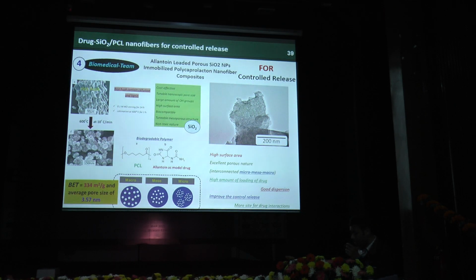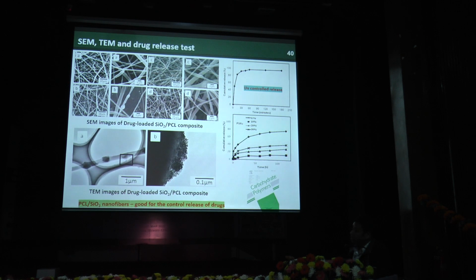And also for some biomedical application, we fabricated silica nanoparticle and we loaded the drug on the silica nanoparticle, and we incorporated it into nanofiber for controlled release property. So here you can see the profile. Even after 100 hours, the drugs are being released. So this is very good for biomedical applications and also for wound healing, even for blood vessels.